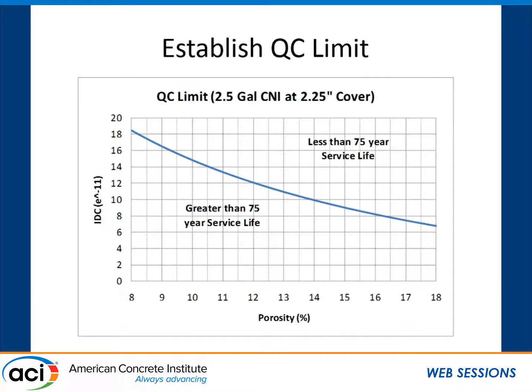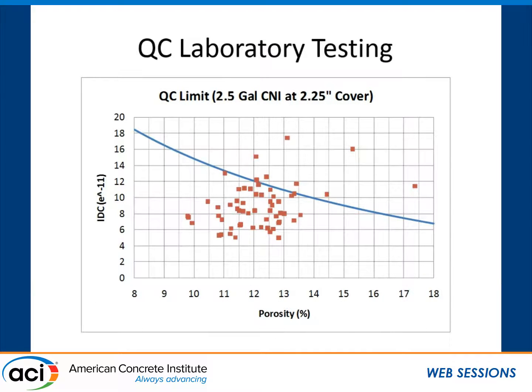When you do enough of these and you have a project that has enough of it, you can develop a curve in which you have your one parameter and the other parameter and the relationship of acceptance and rejection, the combination of the two major elements. You can build a curve so that when you have the data coming in from the field, you can start looking at this and seeing where they comply. If you have points that are outside, these are the ones that may have one number high but the other number low. What you want to do is run that, see if it has an effect. The nice benefit of having that type of an option, if let's say this outlier here had a problem, you have that modeling and you have the prediction of that time. Now you can apply repair or protection systems for fixing that area of a structure if necessary.